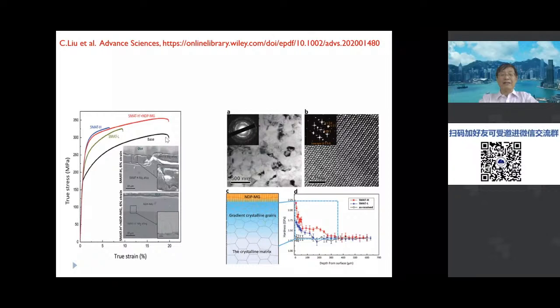But how to enhance the mechanical property of the whole structure? Because what I have shown just before is 10 nanometers thick. So people always ask, this cannot be directly used as a bioimplant. But here I just show you one example. We combine SMAT, surface mechanical treatment. You can see SMAT can drastically enhance the mechanical property, but the elongation is drastically reduced. Then we use this dual phase material to further enhance the deformation capacity to stop the initiation of cracks using a gradient structure. You can see the deformation capacity is quasi similar to the base material, but the yield stress is drastically enhanced.